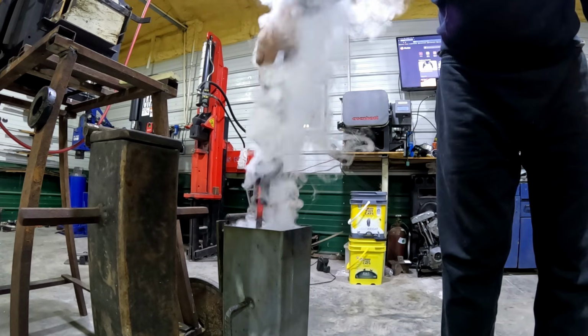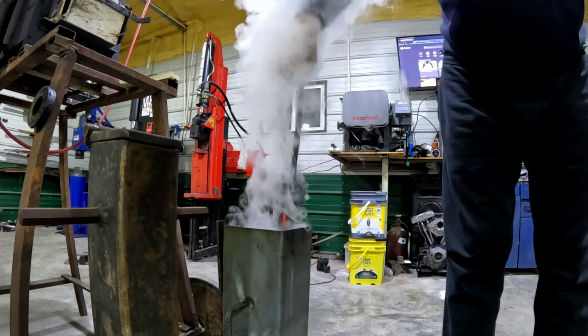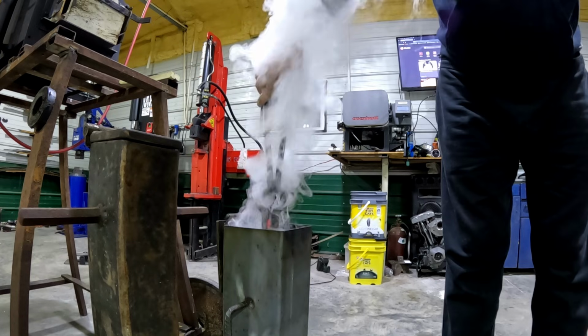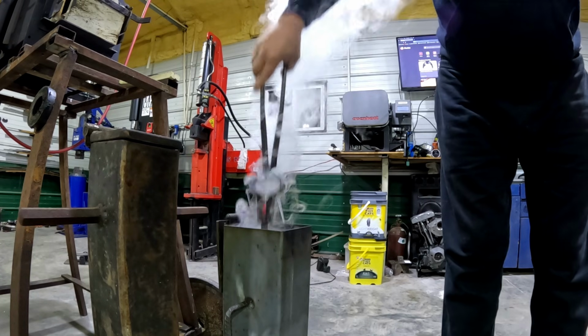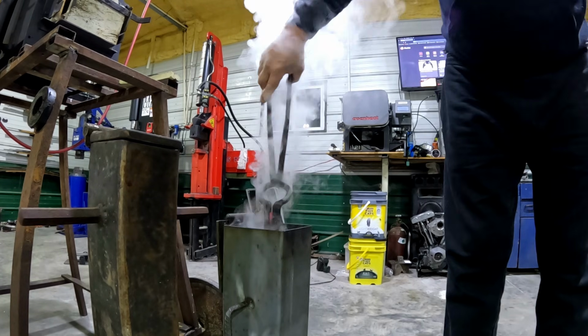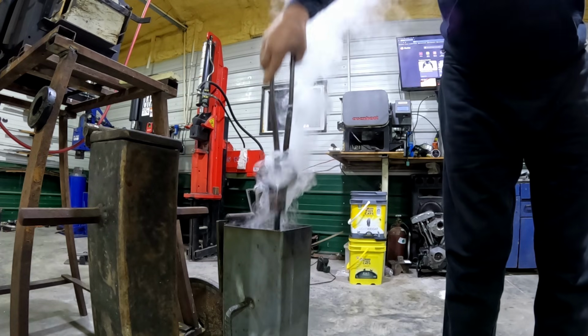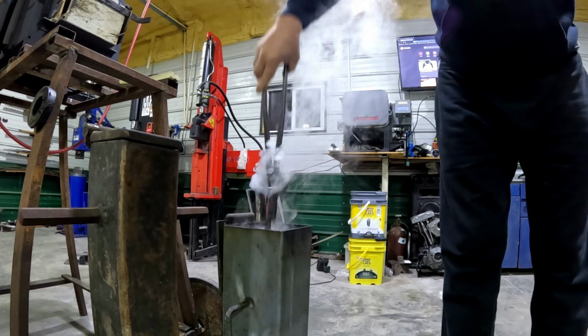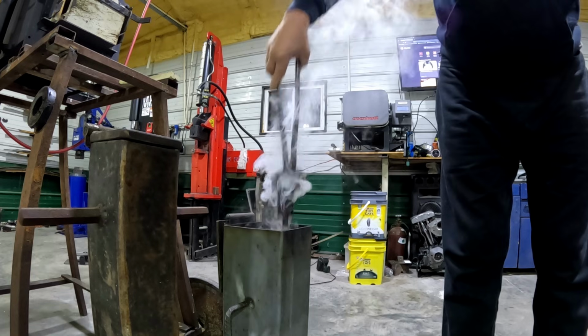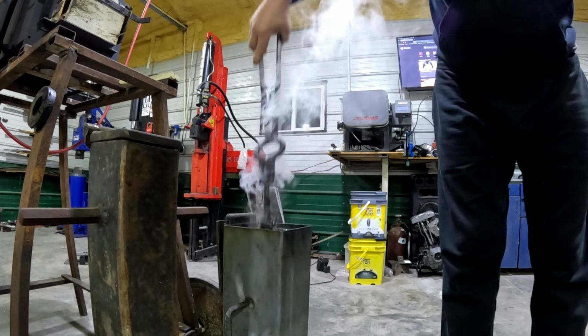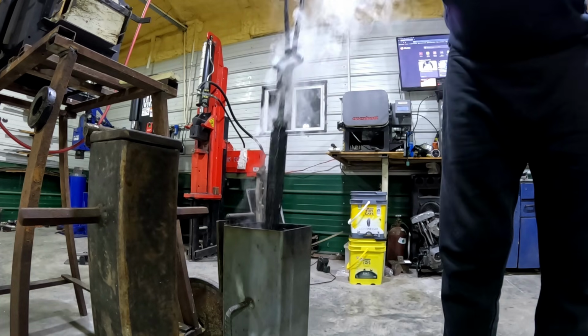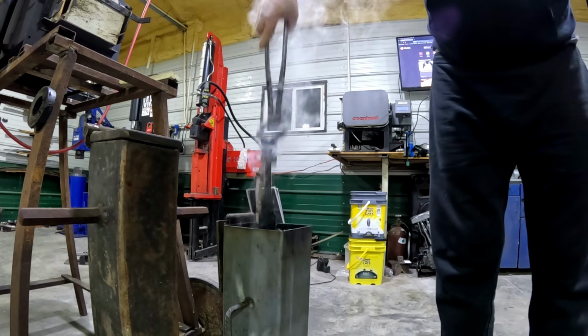That means it's still hot enough to vaporize oil on contact. Translation: not fully cooled, not fully transformed, and not fully hard. Pulling early equals softer martensite, uneven hardness, maybe even pearlite sneaking in. Your edge might roll before it cuts, and the whole heat treat is half-baked. Congrats, you just made a $500 butter knife.